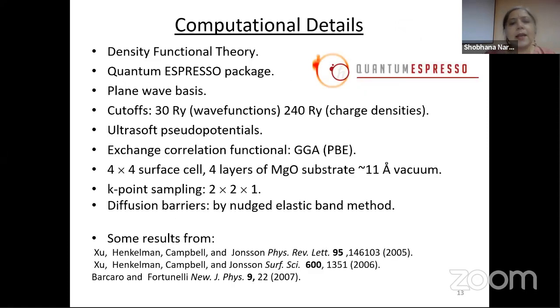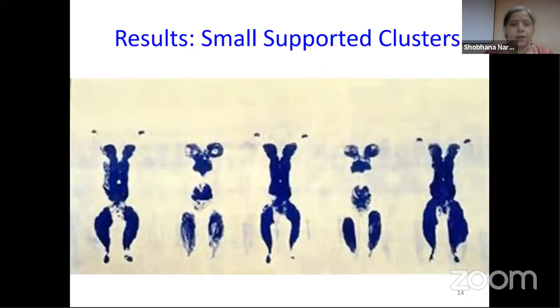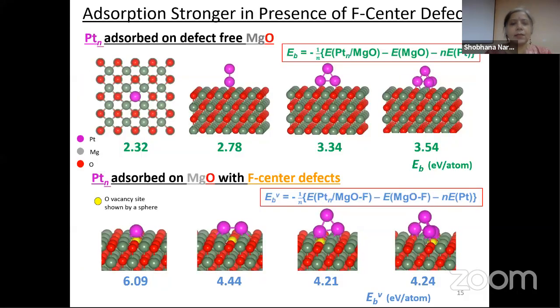And these are pretty standard density functional theory calculations. The only slight thing of interest might be that the diffusion barriers are calculated by what is called the nudged elastic band method. So let me first give you the DFT results. So the first thing we find is just the adsorption energy. So these are the strength by which these small nanoparticles are bound to the surface.